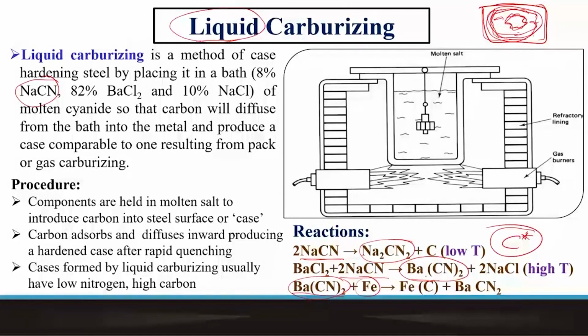So the process involves, instead of a solid pack or a box, we have a bath, we have a heating device through either flame or resistance heating coil or something, so that the salt that we are dealing with, essentially sodium cyanide, should actually be in the molten state. So this is a salt, it has its own fusion temperature. And once it is in the molten state, then it dissociates into a lower compound, sodium cyanamide, and that releases carbon. So essentially one carbon comes out of this dissociation process.